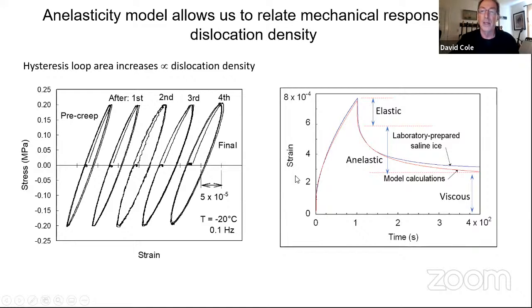dislocation density. If we're looking at time domain behavior, constant load creep test, this is the kind of result that we're talking about, where there's an anelastic strain or an elastic strain, let's say when we unload, this time-dependent anelasticity, and then a viscous strain component. And so generally the model does a nice job on handling all that behavior.